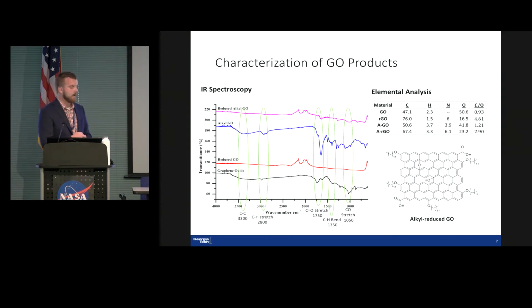CH stretch completely. In the alkylated variant, especially the graphene oxide, it's very apparent, but even in the reduced graphene oxide, we still see this little blip here. It's kind of hard to see on the graph, but there's a little bump there. You're welcome to check this out afterwards if you have any specific questions. And then we can also see a couple other things, a carbonyl peak that disappears upon reduction, as well as the presence of the CO stretch here, which is indicative of the ether linkage that's connecting these alkyl chains to the graphene.